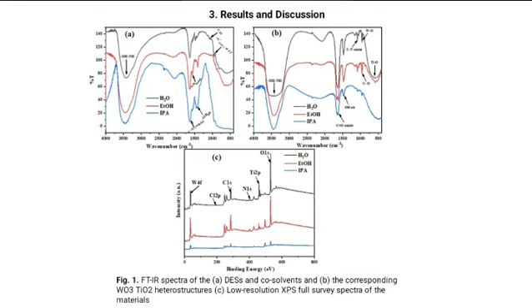Meanwhile, the peaks at 1478 to 1456 wave number were assigned to the alcoholic OH band, which could be due to the choline chloride. However, the weak peaks at 1802 wave number and 954 wave number could be due to the C single bond O and the quaternary ammonium or the chloride groups respectively. The corresponding metal-based heterostructures were characterized by significant changes in the peak intensity and vibrational frequency, which could be due to the interaction between the metal salts and the deep eutectic solvent.